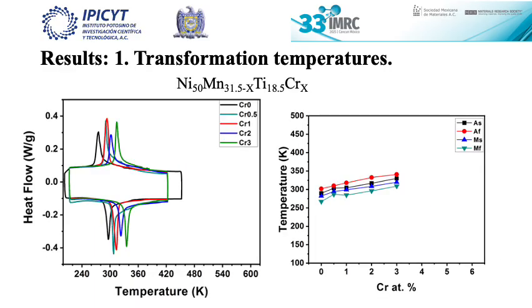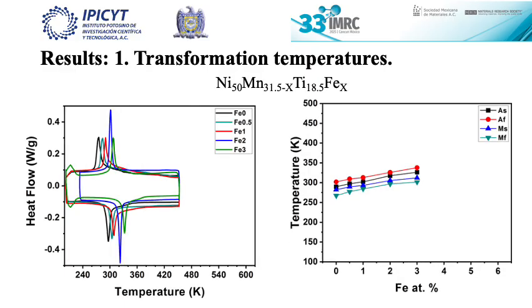For the case of chromium addition, we can see, however, an increase of the transformation temperatures. Also seen for the iron addition, where the transformation temperatures also increase.